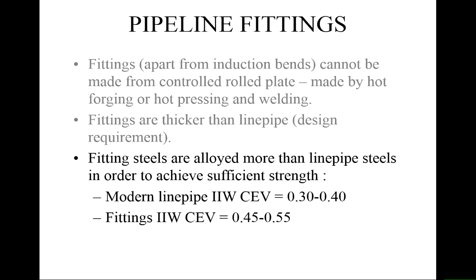Fitting steels are more alloyed. If we look at modern line pipe, the carbon equivalent is 0.3 to 0.4, and for fittings it's 0.45 to 0.55. So fittings are more difficult to weld. I'll say that slowly, because I think I've seen more problems with people expecting fittings to be welded the same as the line pipe when they're not.